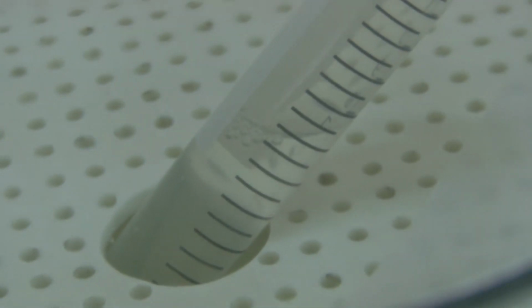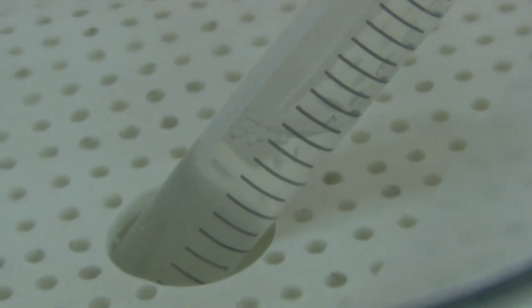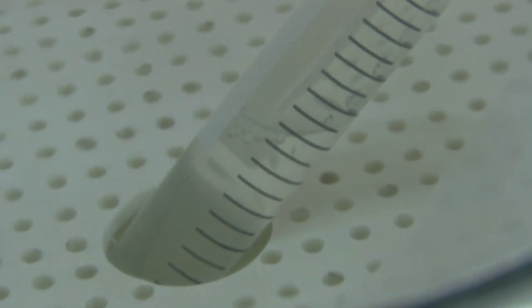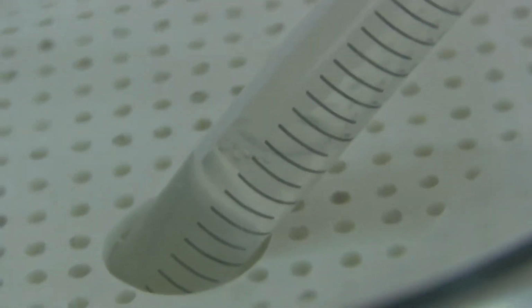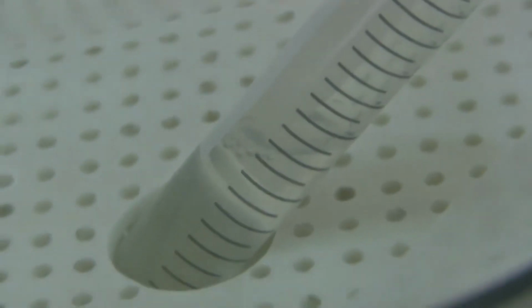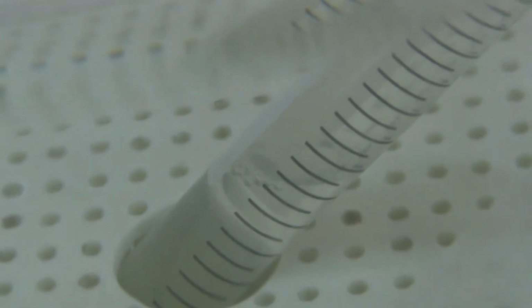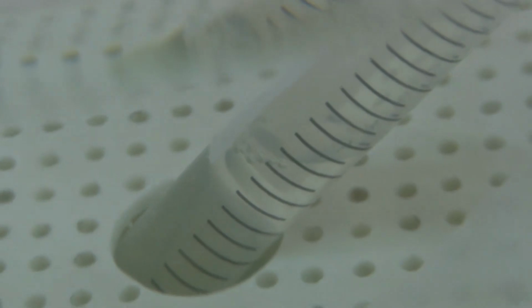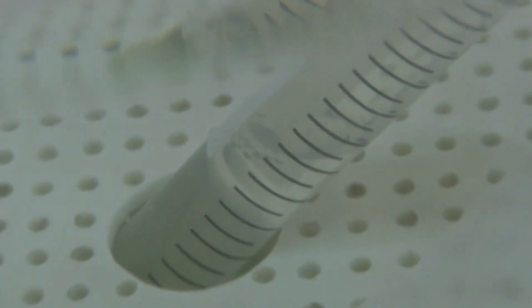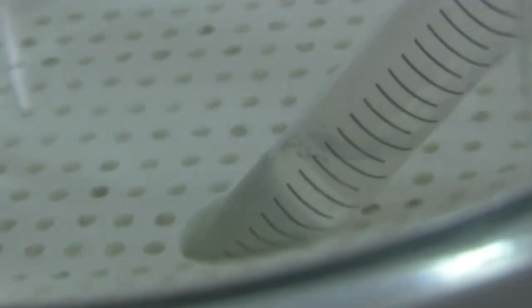So, this was nearly after 10 minutes of waiting. Now this is what you can see. There were a lot of small tiny bubbles inside the mixture, but now there are very few bubbles. So, we will wait for a couple of minutes, say 5 minutes, and then you will be able to see all the bubbles flown out, and inside the vacuum chamber we would get this clear polymer mixture.